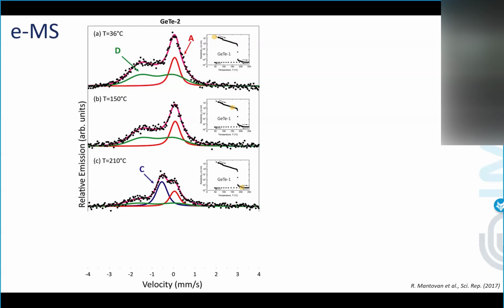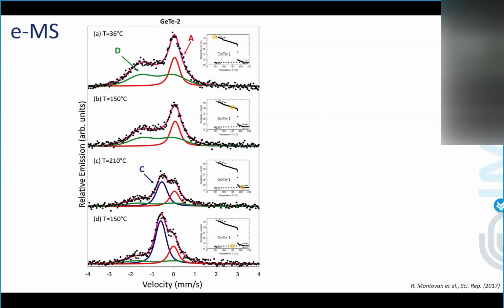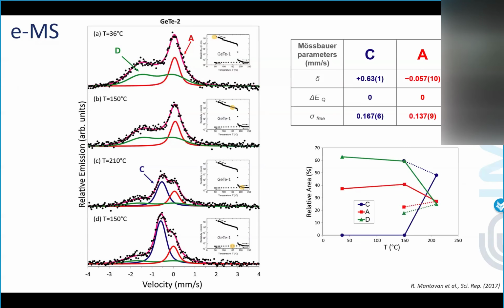And now we have 2 components. And then if you go on, you cannot reverse, because this is done only with very fast laser processing, not with the halogen lamp. You just provide additional thermal budget and the C component goes up. So we identify 3 components in the 2 configurations, the amorphous one and the crystalline one.